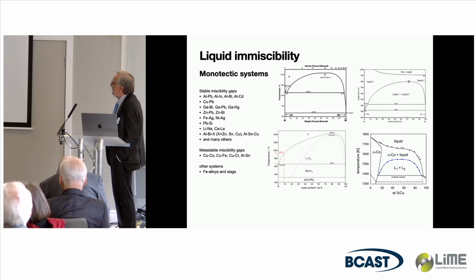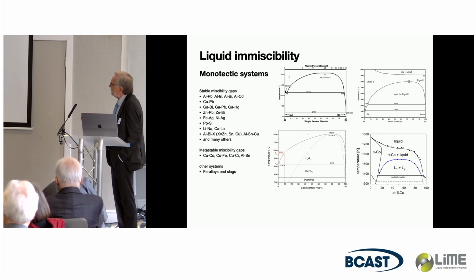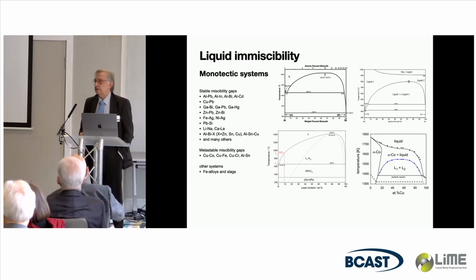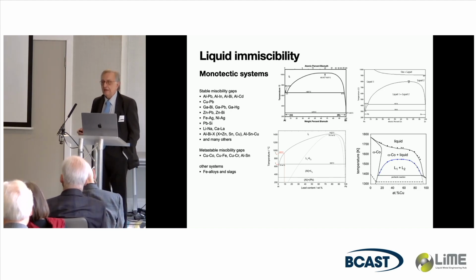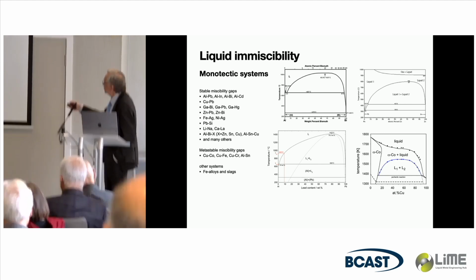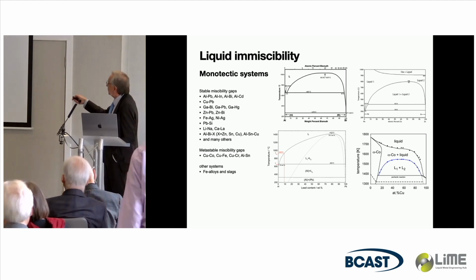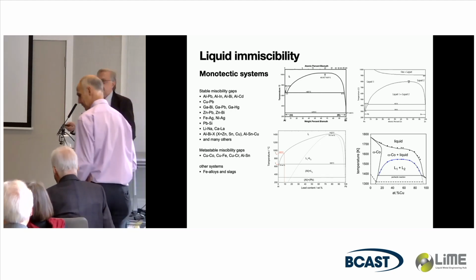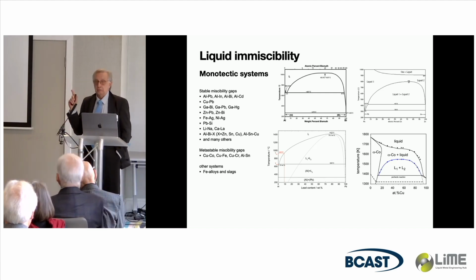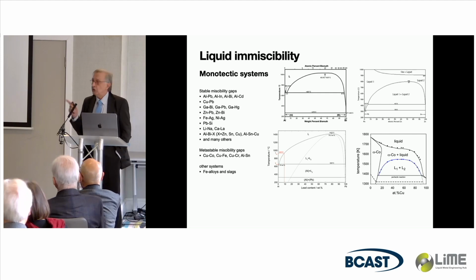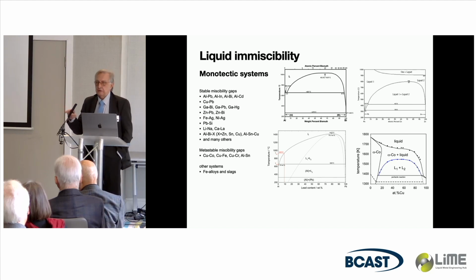And there are a lot of these binary materials which show a liquid miscibility gap. Wonderful. Let me say this: iron-silver and silver-nickel are an exception from all this, because in these materials, if you look into the phase diagrams, you find not even a critical point. They are completely immiscible in the solid and in the liquid state, and such a diagram would look like this: you have the melting point of, let's say, silver, the melting point of iron or nickel above, and that's it. And even from these materials you can make really important materials in daily life. By powder metallurgical methods, you make power switches, which are important for power switching in electrical lines.